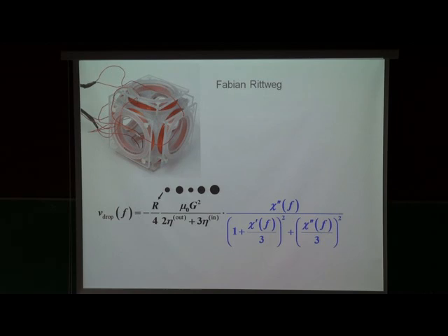So what we did is, we did 2 types of measurements. We measured the drop velocity at a certain frequency, at 500 Hertz, and then we measured the drop velocity at a different frequency where we were interested. And by rescaling that, you see that the first part falls out, and we are ending up with the second part here.